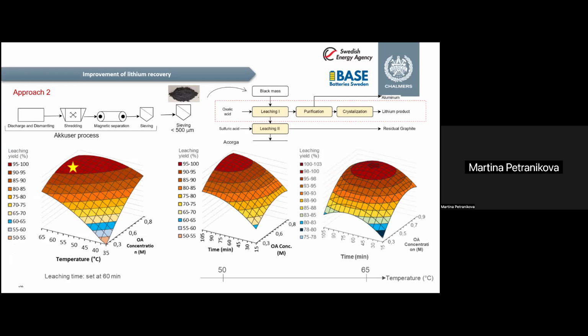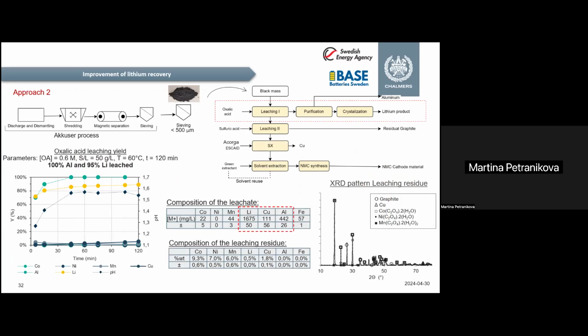So then another way was to use organic acids. And my PhD student, she started to work with oxalic acid and did experimental design and tried to find the conditions where we could selectively recover lithium. And what she achieved was that she was able to recover almost 100% of lithium.